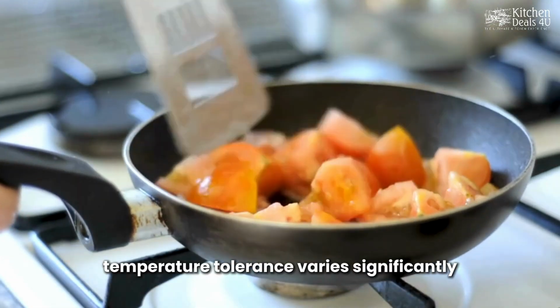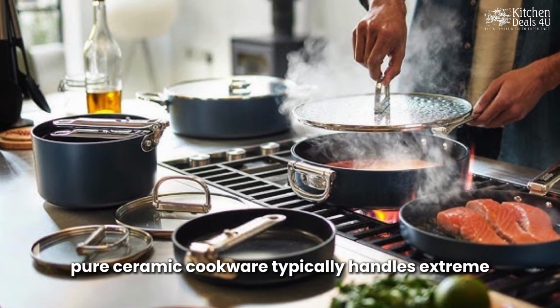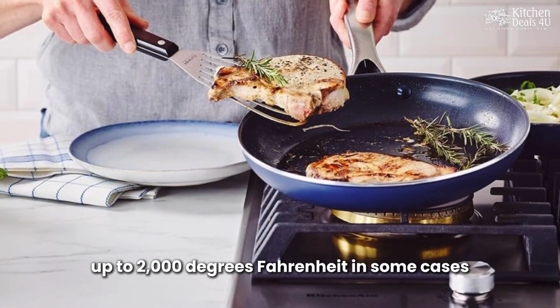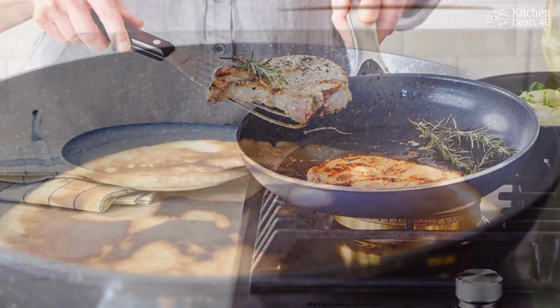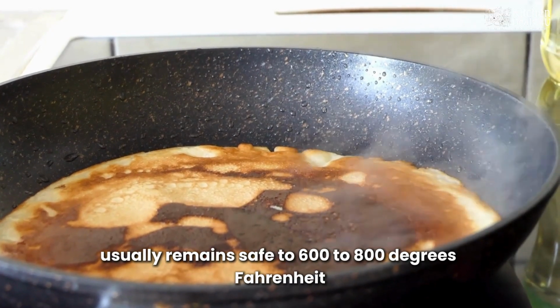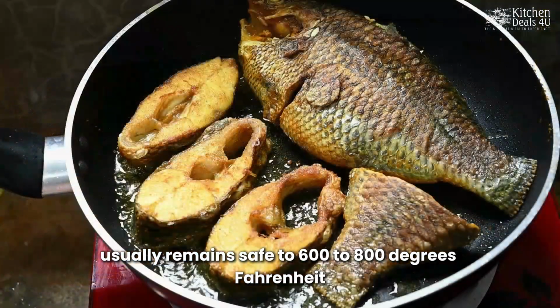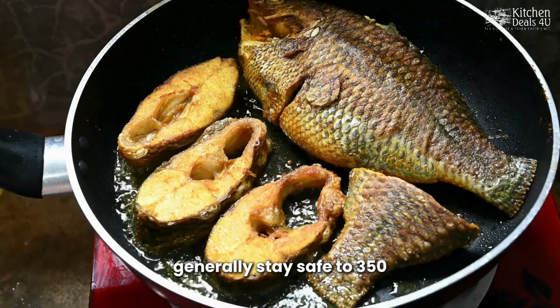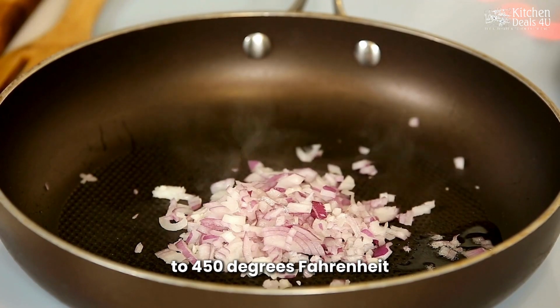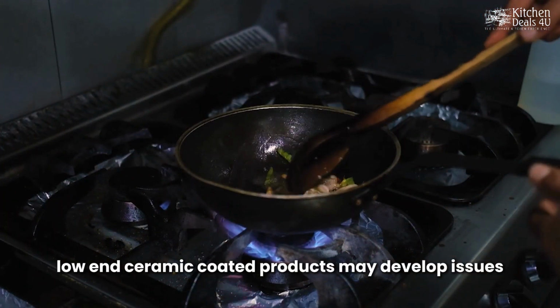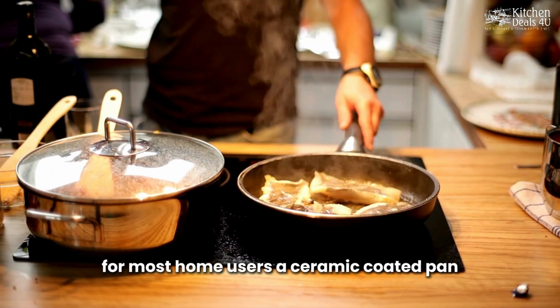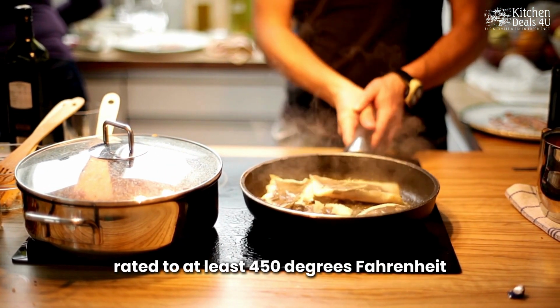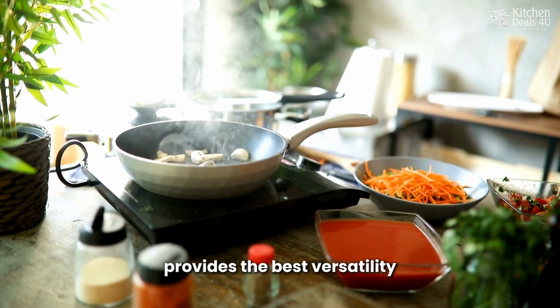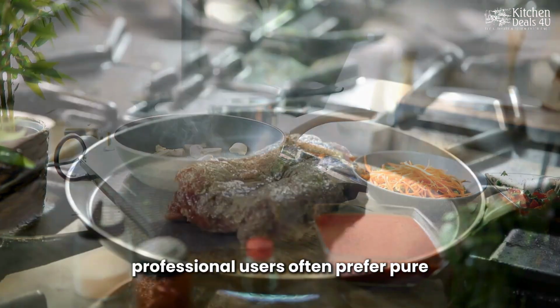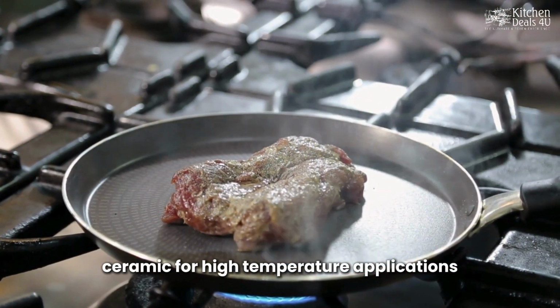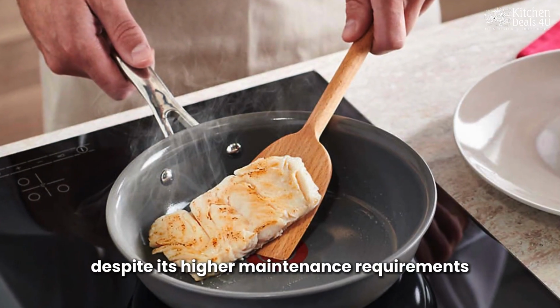Temperature tolerance varies significantly between ceramic types. Pure ceramic cookware typically handles extreme temperatures, up to 2,000 degrees Fahrenheit in some cases. Premium ceramic-coated cookware usually remains safe to 600 to 800 degrees Fahrenheit. Standard ceramic-coated options generally stay safe to 350 to 450 degrees Fahrenheit. Low-end ceramic-coated products may develop issues above 300 degrees Fahrenheit. For most home users, a ceramic-coated pan rated to at least 450 degrees Fahrenheit provides the best versatility for typical cooking techniques. Professional users often prefer pure ceramic for high-temperature applications, despite its higher maintenance requirements.